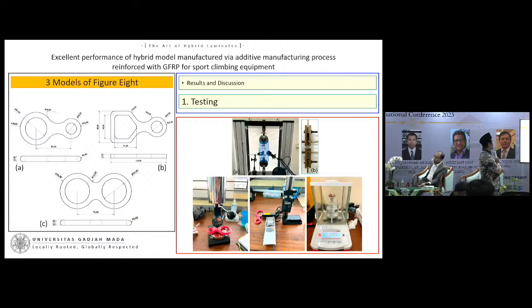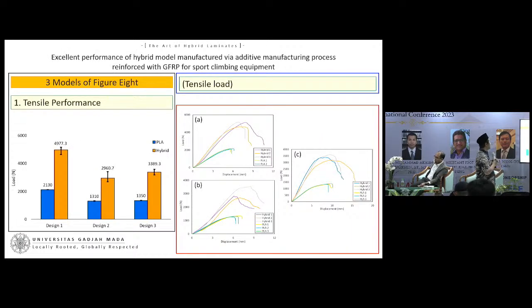Here are the results. From the tensile performance, we can see the results of the hybrid laminates. What is the difference between blue and orange? The blue is only the PLA models that we manufacture using 3D printers, and the hybrid is when we cover it with glass fiber reinforced polymers. We can see almost 100%, about 2 times higher tensile performance.